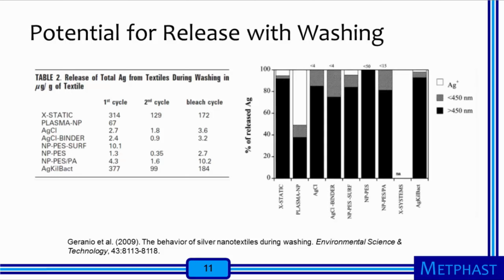In this figure on the right, the releases during the first washing cycle are separated into particles larger than 450 nanometers, particles smaller than 450 nanometers, and silver ions. For all except one of the test fabrics, most of the released silver was in particles larger than 450 nanometers, suggesting that the applied silver is not really nanosilver, or that the silver particles are agglomerated. The plasma NP fabric was the only one known to use silver particles approximately 100 nanometers in mean diameter. Therefore, it is not surprising that less of its released mass was larger than 450 nanometers.